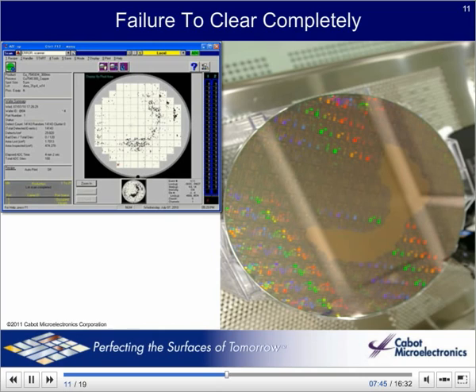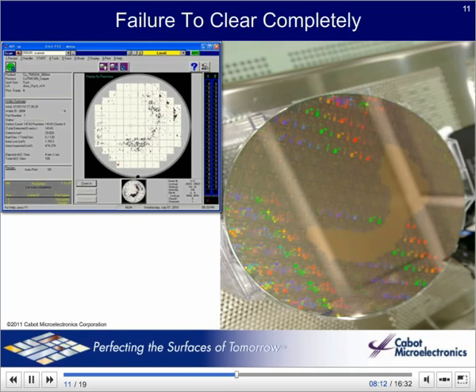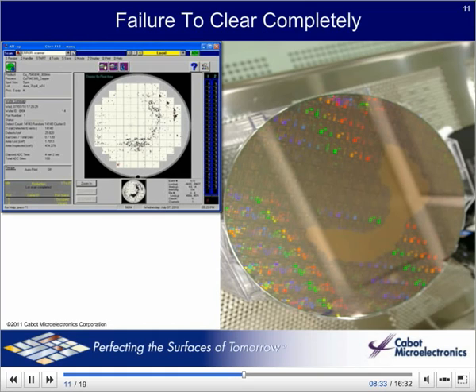Sometimes non-uniformity from polishing results in a partial failure to clear all the surface you are trying to polish. In the images above, you can see in the data on the left and the photo on the right that a large swath of copper is left behind. This is a particularly vivid example of insufficient clearing and non-uniformity. Often it is much less obvious — a few microscopic puddles or some lines that are misshapen. To ensure that all the features are cleared, it is typical to over polish for several seconds, typically 30 seconds or longer. But this comes with drawbacks. The longer you over polish for reactive surfaces such as copper, the process continues to remove material causing topography including dishing and erosion. For more inert surfaces like oxides, over polish can lead to scratches.